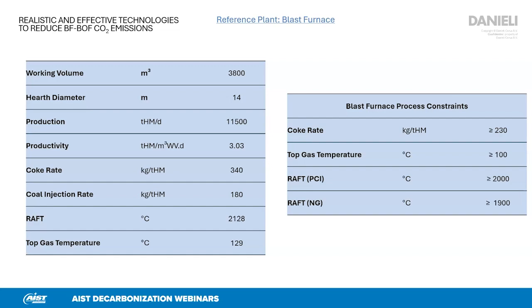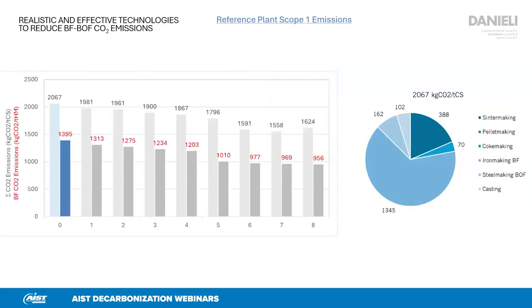And I would say the other key KPIs are rather reasonable. Within the spreadsheet model, we've actually been using the detailed results of our thermodynamic blast furnace steady state heat and mass balance model. But we've also been assuming realistic constraints as these are commonly accepted in our industry on minimum coke rate, minimum top gas temperature, and RAFT for using PCI or natural gas.